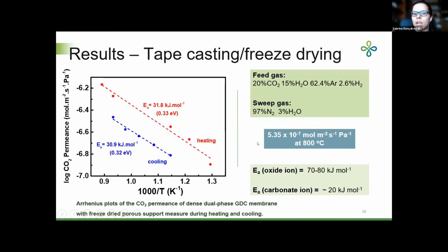And it's interesting that the activation energy for permeation, that is the energy necessary to start the formation and the transport of these carbonate ions, lies between the activation energy of the oxide ion and the typical value found for molten carbonate.